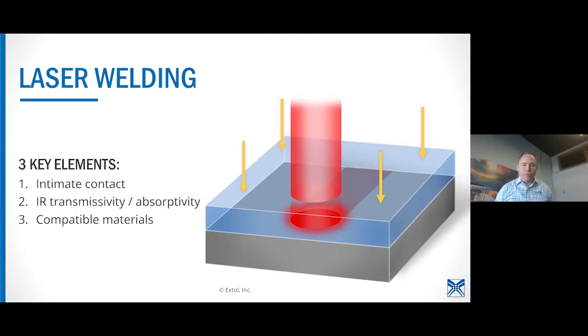So hopefully that came through for everyone okay, and just gives a sort of compact description of that. And so just to recap, because it is so crucial and actually is a precursor to some of the myths that are out there regarding laser plastic welding, the three key elements, as we call them in Extol, are intimate contact, IR transmissivity and absorptivity, and compatible weld materials for the welding. And to ensure proper heat conduction, that's what that intimate contact is all about. And that's done via the right sized press, tooling, and weld geometries.